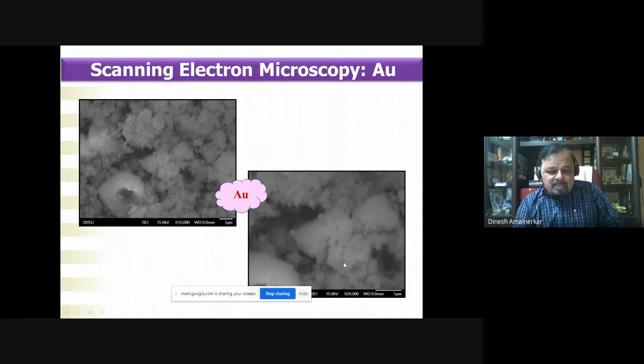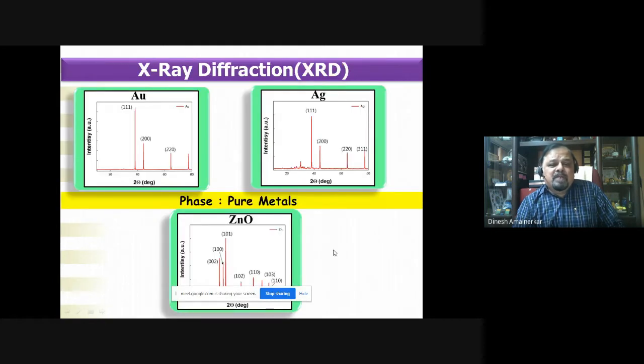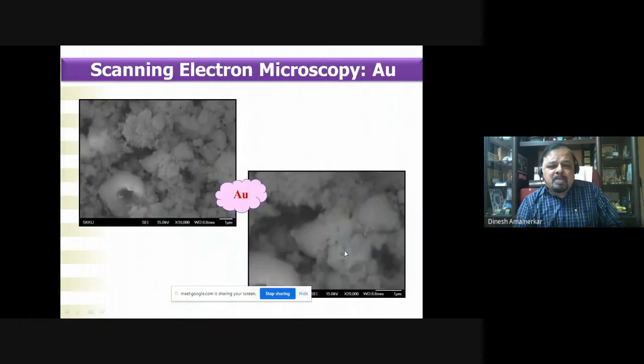So the nanoscale materials here are embedded in an inorganic matrix, which we felt must be amorphous in nature, because if you go back to X-ray diffraction, we didn't find any phase other than metallic gold with the FCC structure. So that was the conclusion: it must be something else, maybe some inorganic ingredients. There is a temperature involved. Obviously, you can't expect any organic to be retained as a result of multiple heating of this final composition. So we felt that nanoparticles or nanogold embedded in an amorphous insulating matrix create complications for the SEM images.